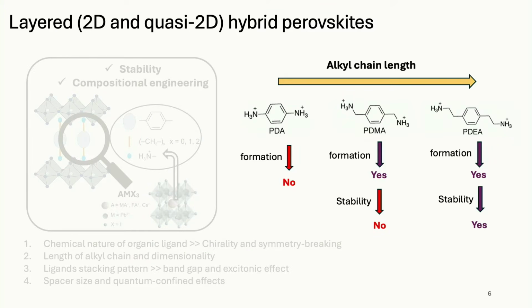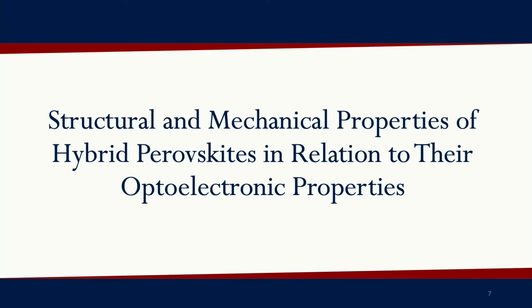But look at this. If you take just a benzene ring with two ammonium groups, it turns out this doesn't form a layered 2D perovskite. If you then put one, I don't know if you know this notation, this means there's one additional carbon here with two hydrogens, so it's a little bit longer molecule. This one will form, but it turns out not to be stable. But amazingly, if you just extend further with two carbons on each side, spacing the ammoniums away from the benzene ring, it'll form and it turns out to be stable. So this just gives you a glimpse that there are many parameters for materials design that are opened up by this complex set of materials.